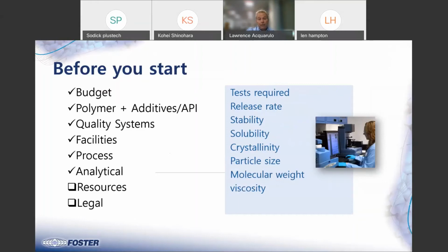The test methods, and again, some of the test methods may need to be validated, but the things that are important, if it's a drug: the release rate, the stability of the drug, solubility of the drug, is the drug going to stay stable, and so forth. The crystallinity of the polymer, which we can check. Particle size, if there's an ingredient going in there.